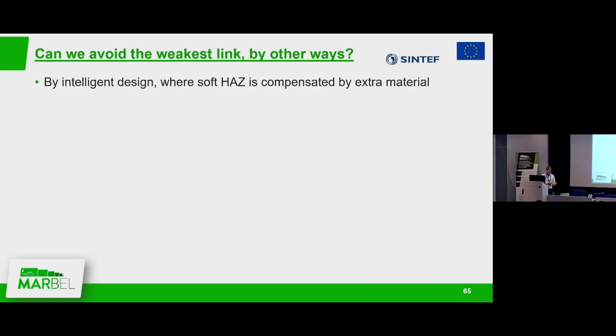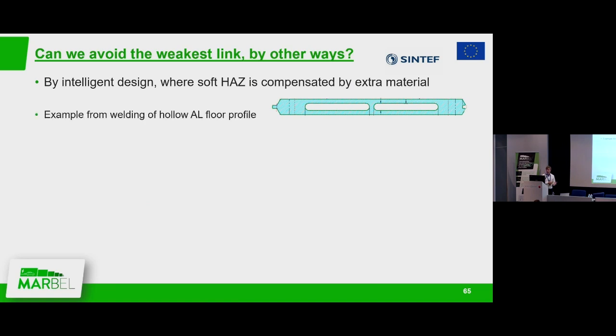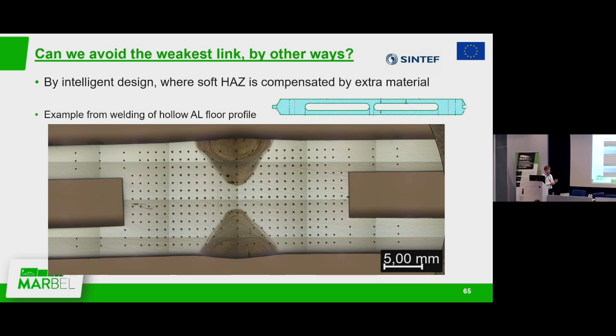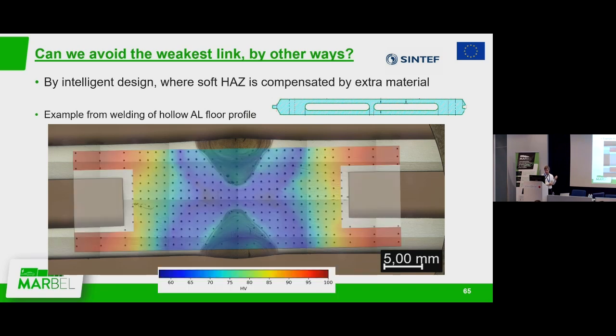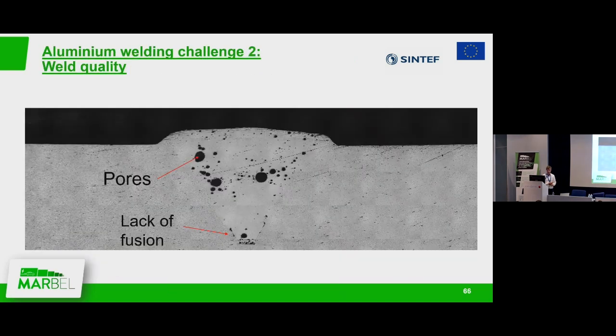We use what we call intelligent design, where we compensate the heat affected zone with extra material when it is needed, but not more. So we designed this component here, which is the bottom floor profile, which is hollow. You see, it's a prototype, so it has squared edges, but it is actually rounded. If you do this with the right heat treatment and the right welding process, we localize this weak area, the blue one, only outside. So this profile here is as strong as the softer, narrower ones, and this creates an evenly balanced strength of the whole profile. So this is the good thing.